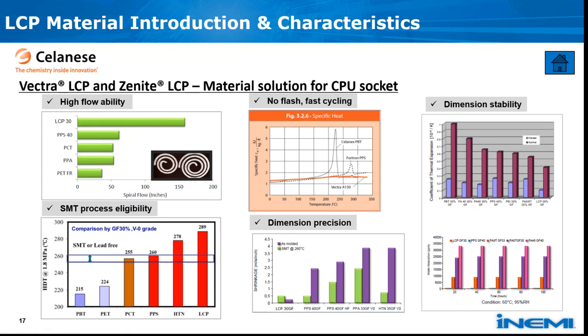In aspect of thermal resistance, it has the highest HDT temperature among the typical high heat polymers. Because the volume change from liquid phase to solid phase is minimum, LCP leads to excellent dimension precision. In the working environment, LCP has a lower CLTE and also lower water absorption. Then these two factors lead to the very good dimensional stability.